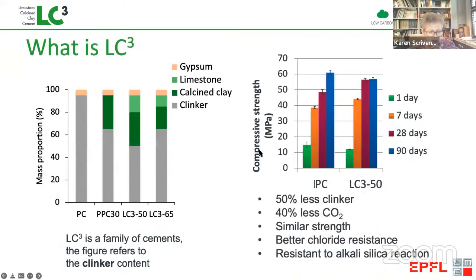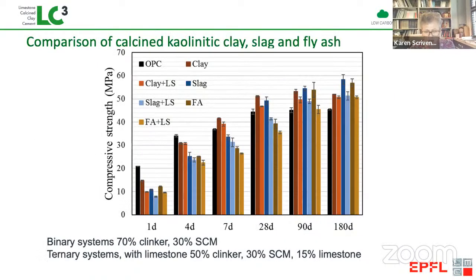So here we see strength results from what we call LC350. LC350 contains 50% clinker, and even though you have to put in some energy to calcine the clay, this means 40% less CO2. And you can see here at 7 days, you have higher strength than your reference. And you also have some properties like resistance to chloride ingress, which are very much improved.